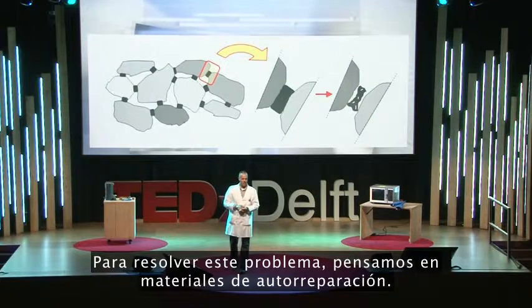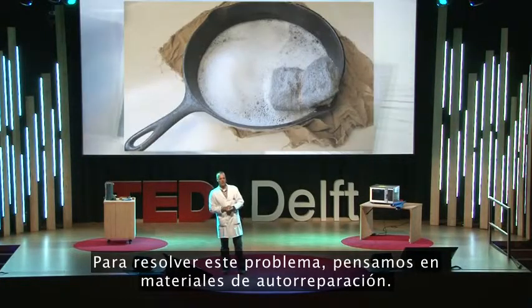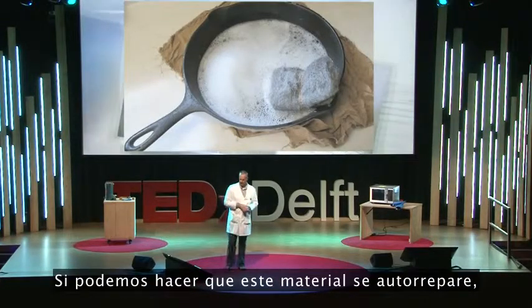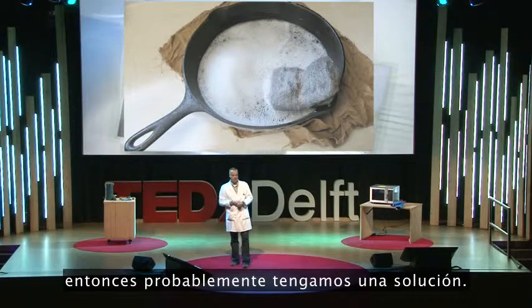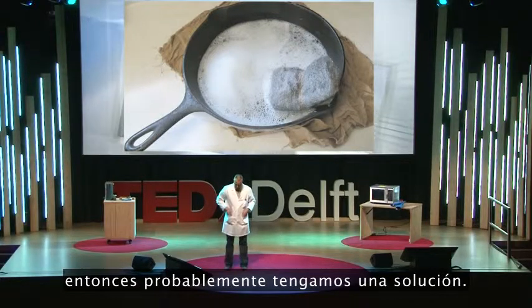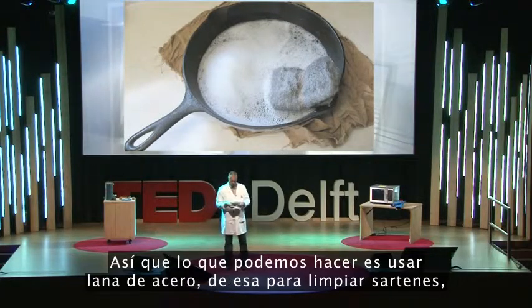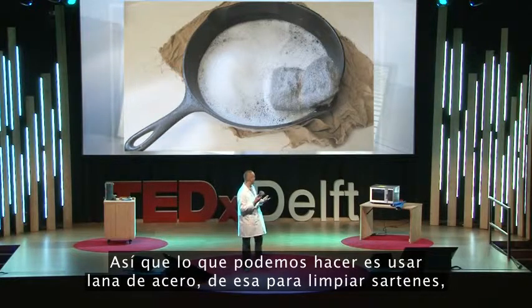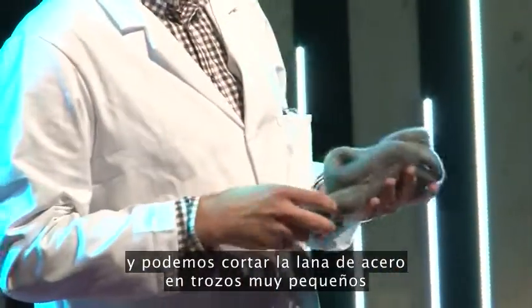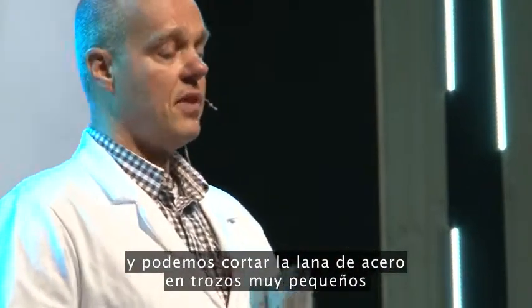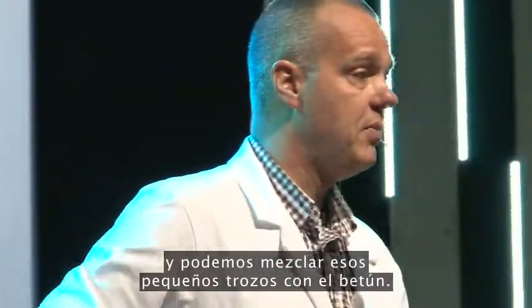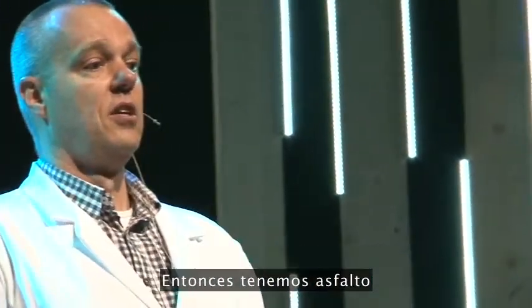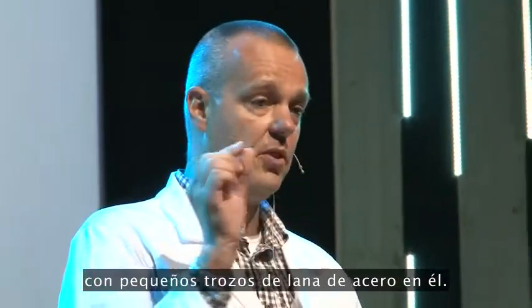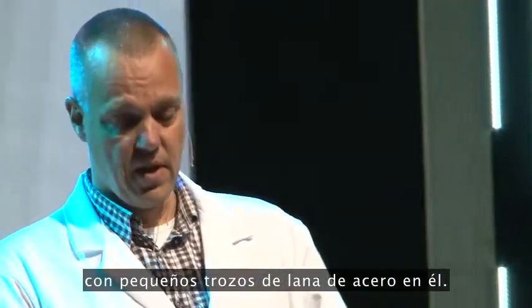To solve this problem, we thought of self-healing materials. If we can make this material self-healing, then probably we have a solution. So what we can do is use steel wool, just to clean pans. And the steel wool we can cut in very small pieces. And these very small pieces we can mix through the bitumen. So then you have asphalt with very small pieces of steel wool in it.